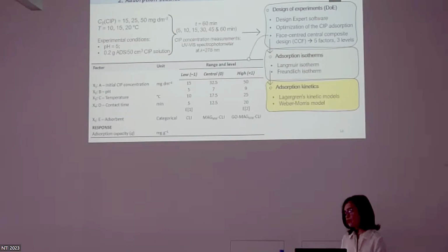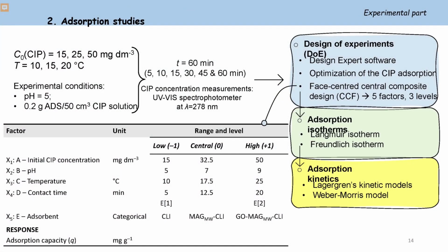So the adsorption experiments were performed by batch method at different initial ciprofloxacin concentrations and temperatures. The ciprofloxacin concentration in the filtrate after the adsorption was measured by UV spectrophotometer. The data were statistically analyzed using the central composite design to obtain the optimal conditions of the ciprofloxacin adsorption of each of these adsorbents, and the used ranges and levels of the design are given here in the table. Then the equilibrium data were analyzed by commonly used adsorption isotherms and kinetic models.